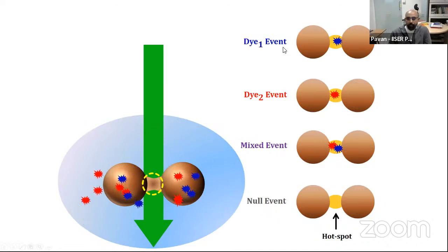And if you are in a single molecule regime, you end up getting a majority of the events in Dye1 event or Dye2 event. The distribution for mixed and null events are suppressed drastically. Whereas if you actually now take a large concentration of the molecule, the mixed events and the null events actually become more. And therefore, you will actually end up with a Gaussian distribution. Whereas if you now are in the single molecule regime, you actually get something called a truncated Pareto distribution. Okay, I'm not going to go into the details of the statistical aspects of it, but if somebody is interested, I would be very happy to discuss. I have some backup slides for later on.